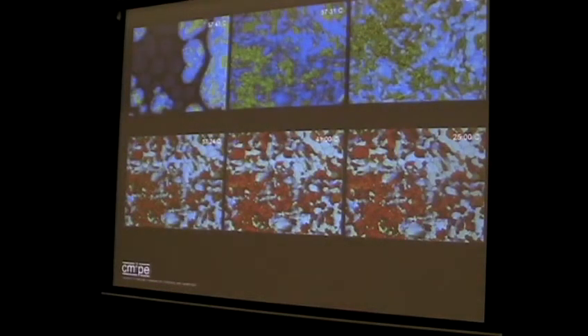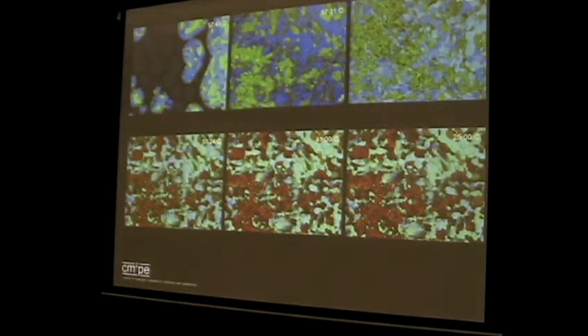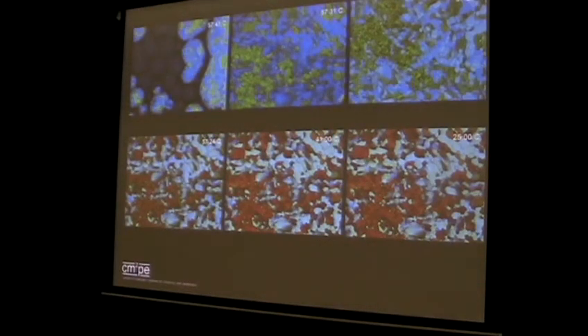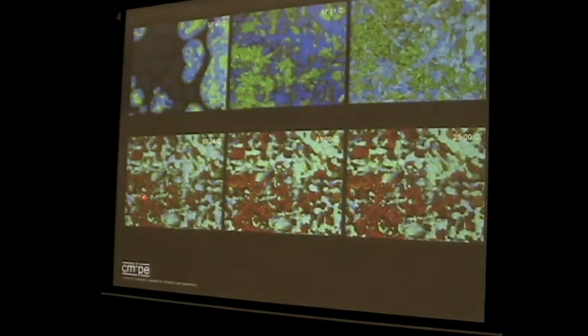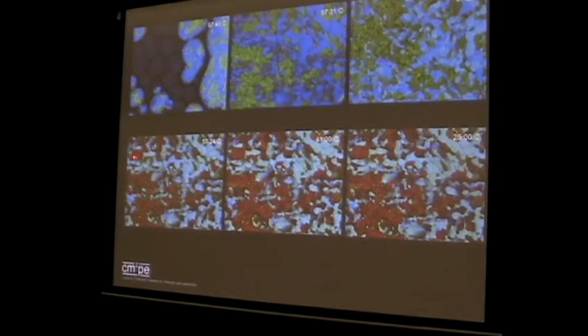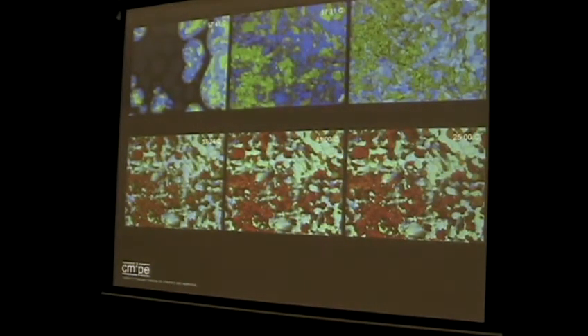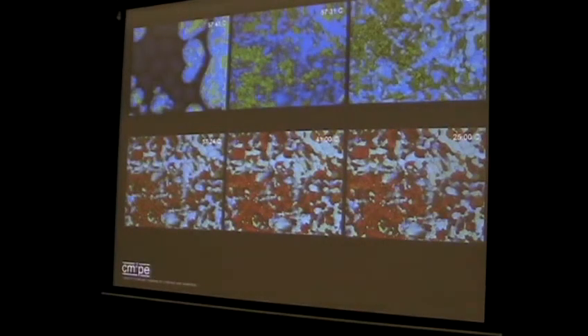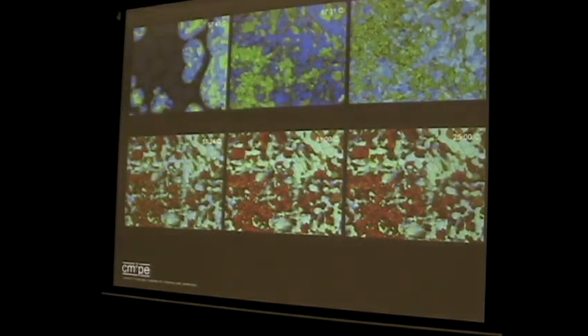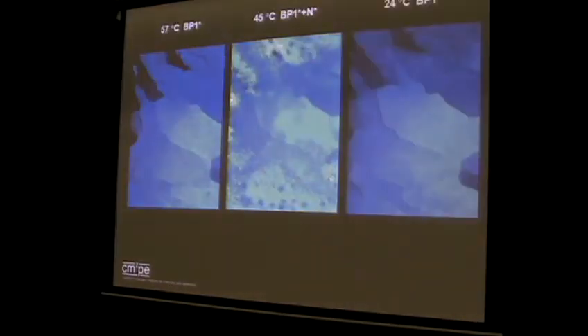recognizing the blue phases. So, you get these platelet textures where you formed carbon structures that form these cubic indices, face-centered cubic or simple cubic, and they're random in space, and they are the platelets. So the colors correspond not to impure material, but to different orientation, different directions of order. Okay, so that's stable. You go down to 25 degrees, come back up, and you see the same sort of transition. Now, I promised to show you a blue phase that was blue. Not any of them are blue.